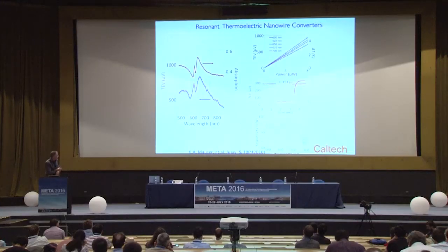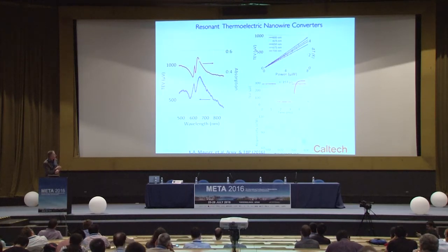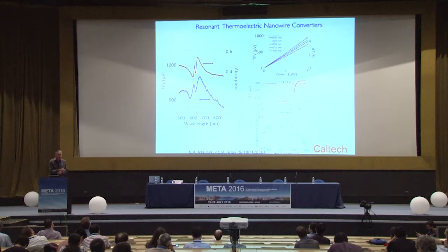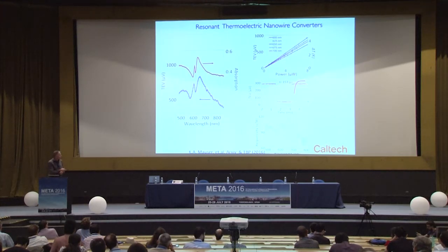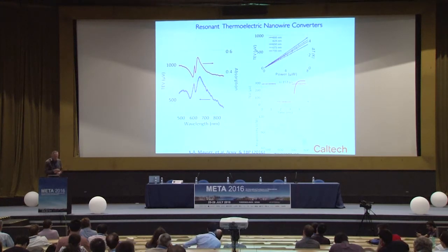And with these resonantly excited guided mode resonance thermoelectric wires, you can see here a very nice correlation between the absorption and the detected voltage induced by the Seebeck effect, which is linear in the power. Because of the very low heat capacity of these nanoscale wires on a thin membrane, they have quite a fast time response in the range of a couple hundred microseconds. The responsivity is not nearly as high as that for a semiconductor detector, but it's acceptably high. We've done quite a bit of detailed study of the spectral detectivity and noise properties that I don't have time to tell you about.